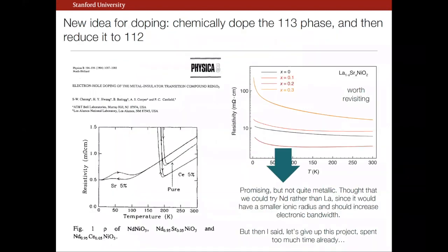So another kind of a lucky accident motivated this idea, which was we had tried to make the infinite layer structure and then subsequently dope it. And I don't say it can't work, but we couldn't do it. So the idea was, why don't we substitutionally dope the perovskite phase and then do this reduction chemistry?